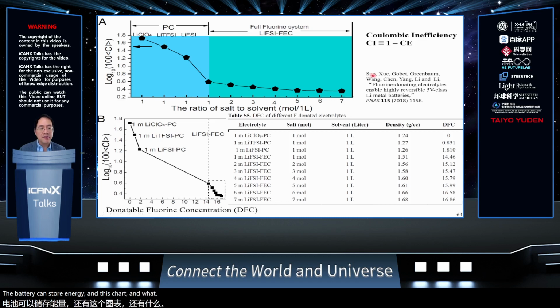And what my previous postdoc, Liu-Min Suo, has found was that when you use different electrolyte solvents and salts, this Coulombic inefficiency exponentially depends on the amount of fluorine in the electrolyte, called the donatable fluorine concentration. And therefore, by increasing the amount of fluorine, you can exponentially reduce the Coulombic inefficiency and increase the cycle life. And that's very good. And in fact, fluorine and also other electrolyte additives can also improve the safety as well.